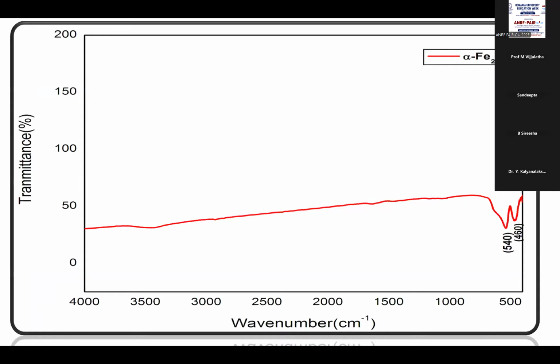And next are the bondings in iron oxide, because we have to again coat it with the polymer. Therefore FTIR studies were also carried out, and it confirmed iron oxide-based bondings. One shows at 540 centimeter inverse and another at 460 centimeter inverse. This is what we have studied.